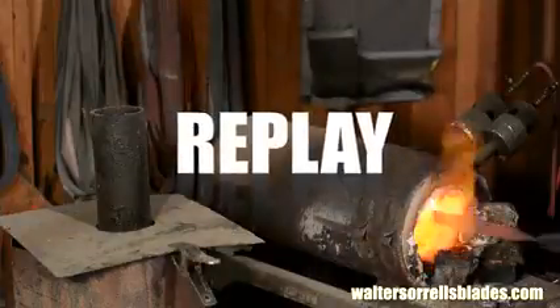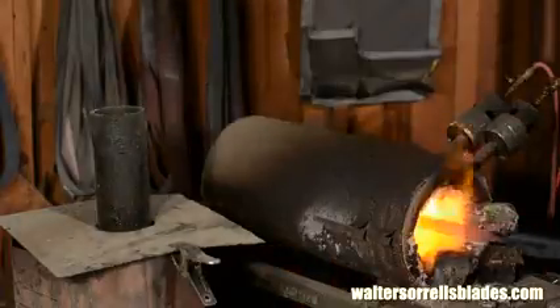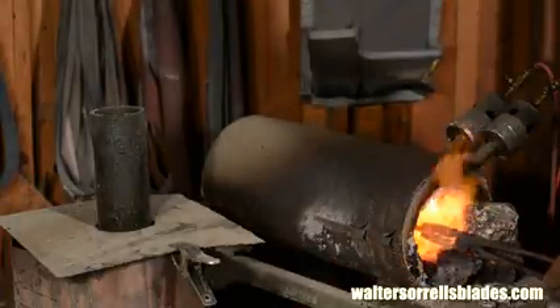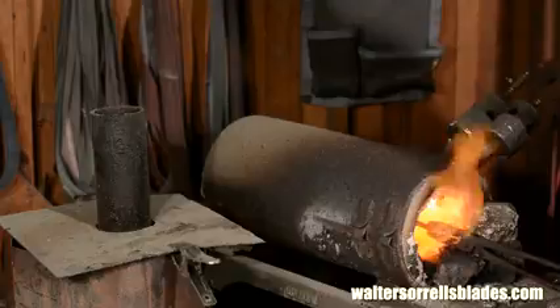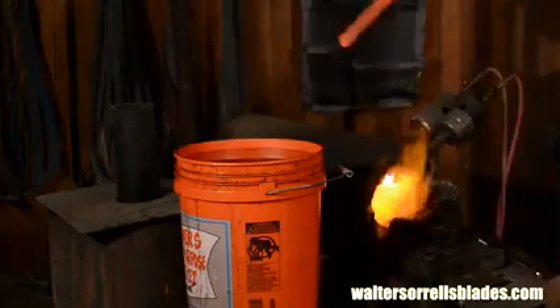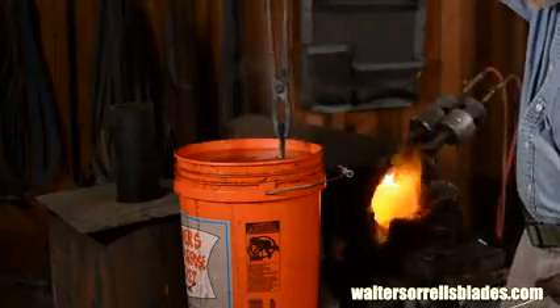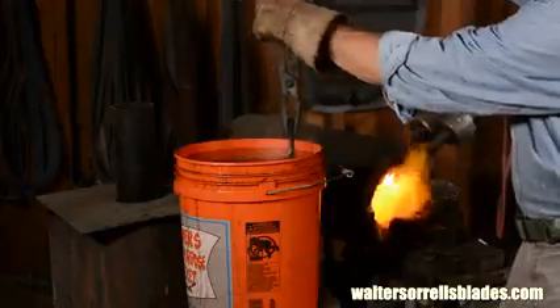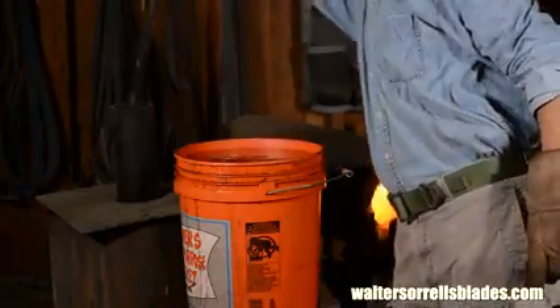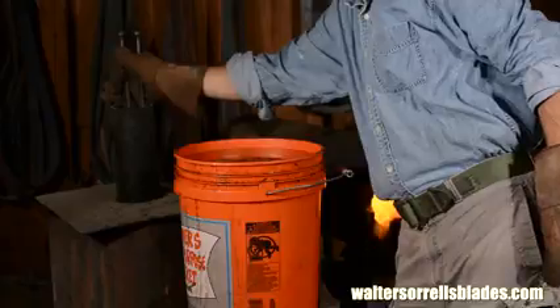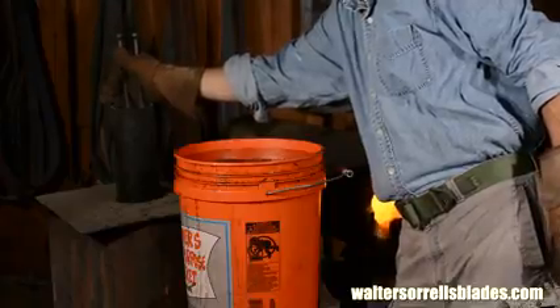So, now the steel's hot enough that the magnet won't stick to it, so I'll just heat it a hair more, making sure it's uniformly hot. I can gauge that by making sure that the color is even all the way across the tool. Now, I go boom, directly into hot tap water for about 3 seconds. Note, I'm only immersing it up to the end of the blade. That'll leave the tang soft and resilient.